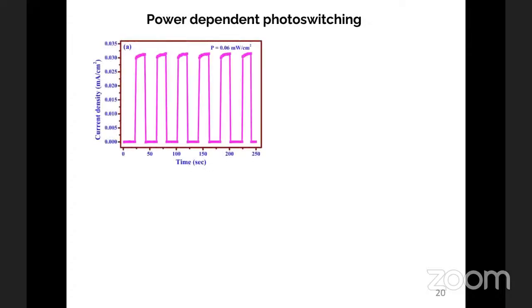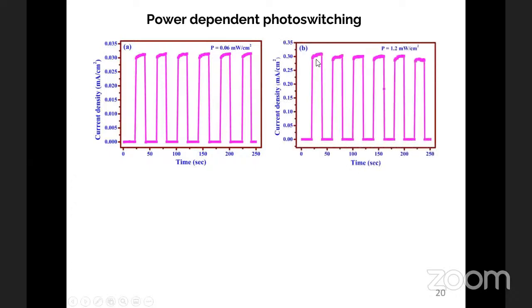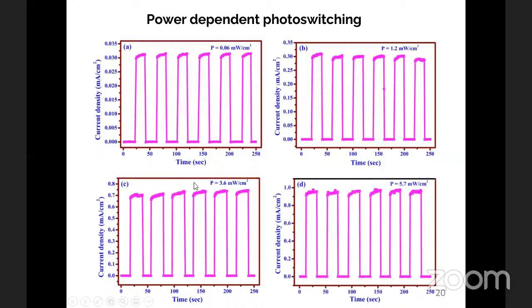The other important thing is power-dependent photo switching. I also checked the continuous behavior, in other words the quality of the materials, by exposing them to several cycles at different laser powers. All of them exhibit a clear, perfect switching behavior for all the different laser powers.